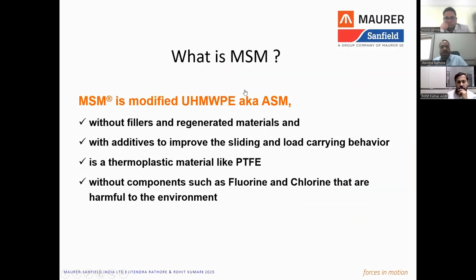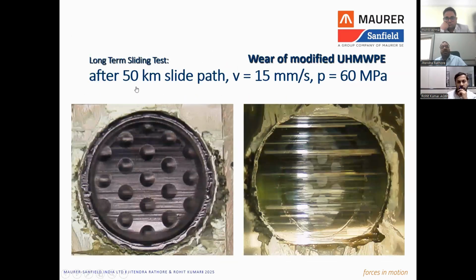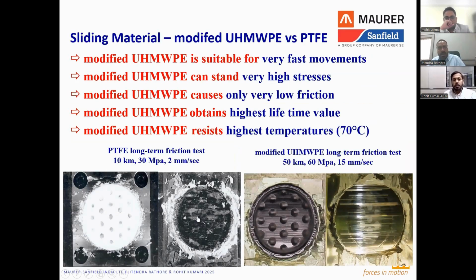parameters. So the advantage of this modified sliding material is that it offers a substantially high improvement in the total slide path. In case of PTFE 10 kilometers, it can go up to 50 kilometers. In case of PTFE sliding velocity of 2 millimeter, it can support up to 15 millimeter. And the stress level, load carrying capacity is also double that of PTFE. So if we have a side-by-side comparison, we can say that whatever were the limitations of using PTFE in bridge bearings, these have been not only overcome but surpassed by a great margin with these modified sliding materials or